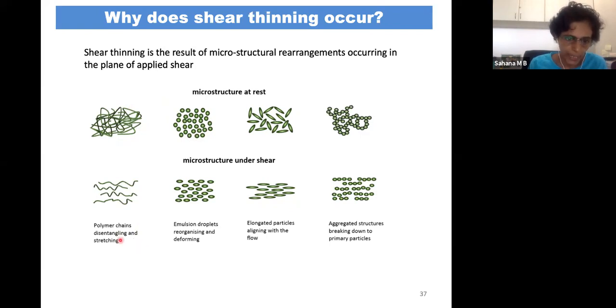And then when we apply the shear, the polymer chains disentangle and stretch. That is why the thinning happens. It can easily flow afterwards. So yield stress is basically the minimum force that is required to change from this structure to this structure, and after that it flows. Similarly, in the case of small spheres, during the resting time this is the microstructure, and this is what happens after it crosses the yield stress.